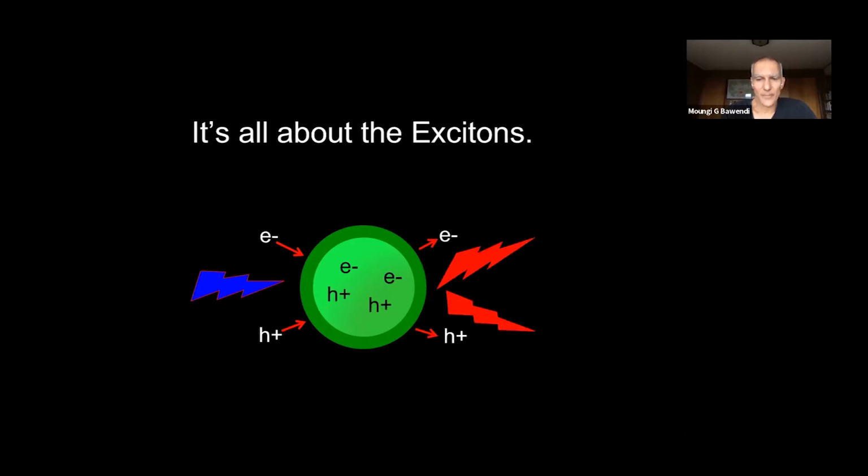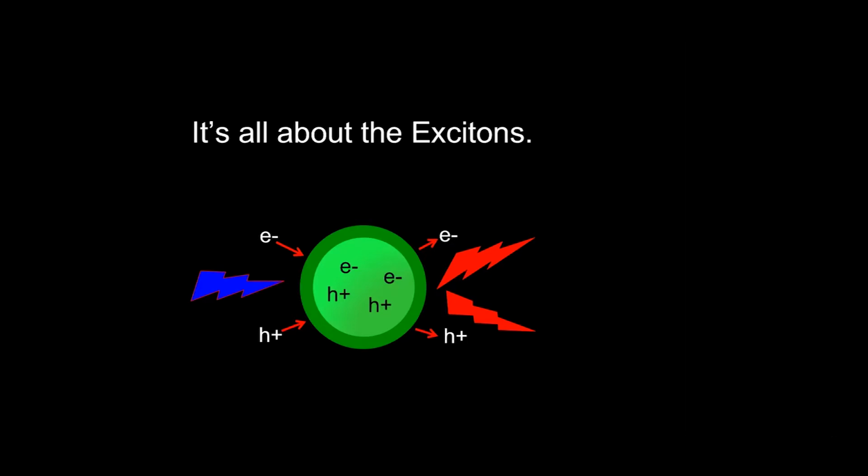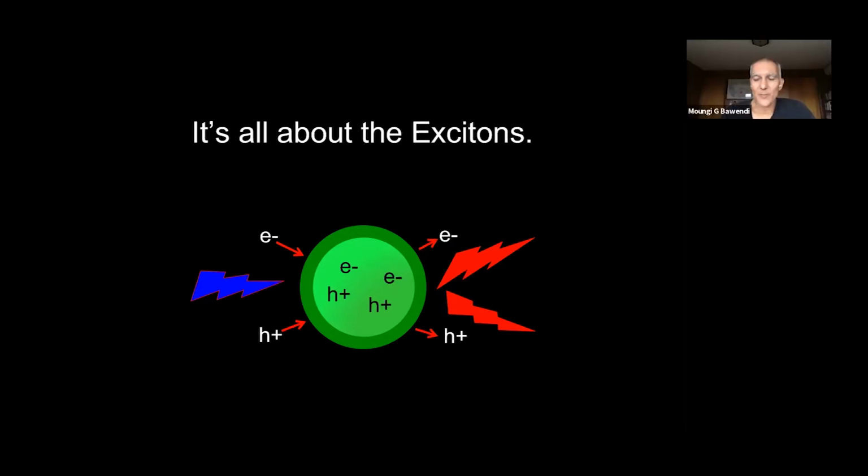You can have multiple excitons, those are called bi-excitons or multi-excitons. So you can cram in multiple electrons and multiple holes. Each one is a separate wave and they interact with each other. So there's an interaction energy. There's a Coulomb energy between the electron and the hole. There's a Coulomb repulsion between the electrons, and all these come into play, and you can build simple models of just a particle in a sphere with an effective mass in the small sphere with simple Coulomb interactions, and you can mimic the properties of these quantum dots pretty well just with these simple models.